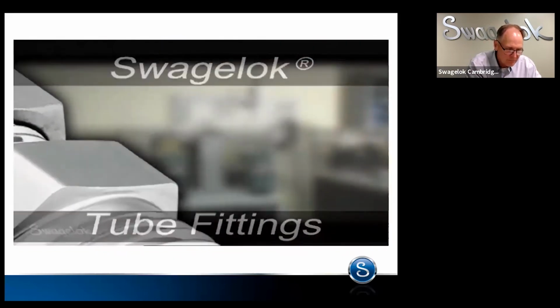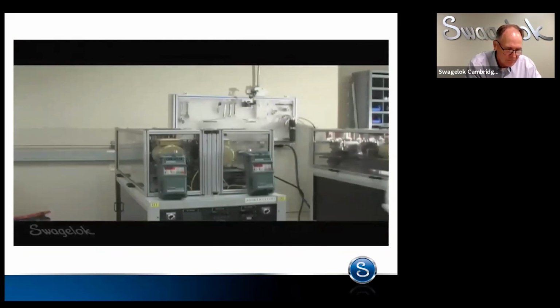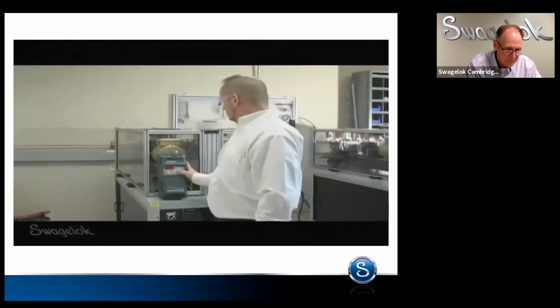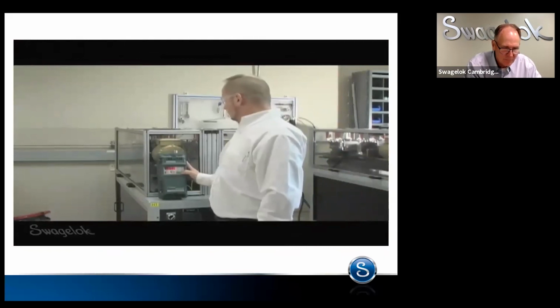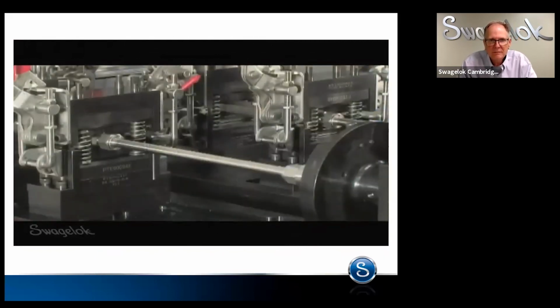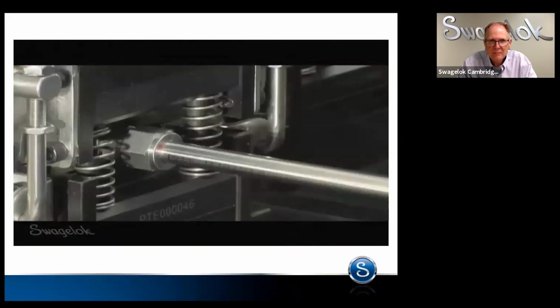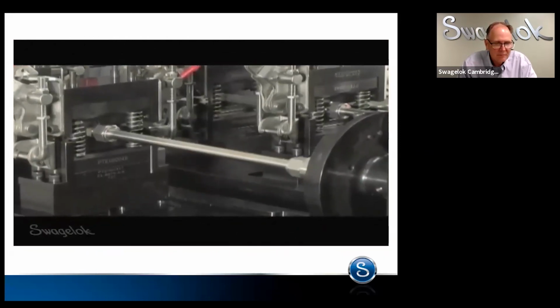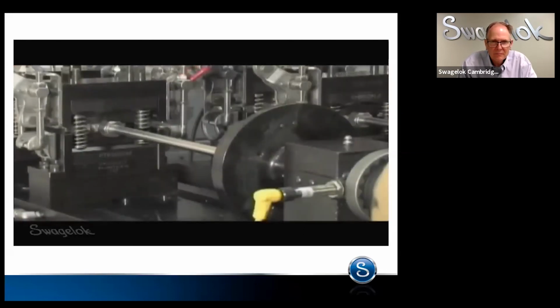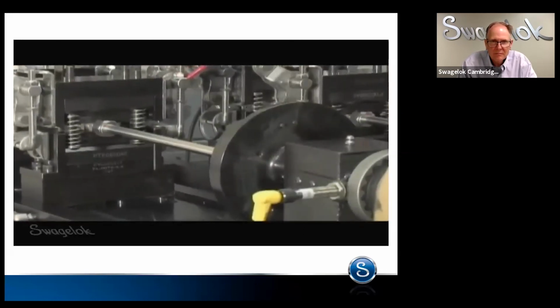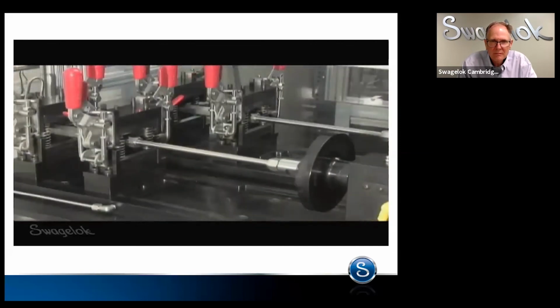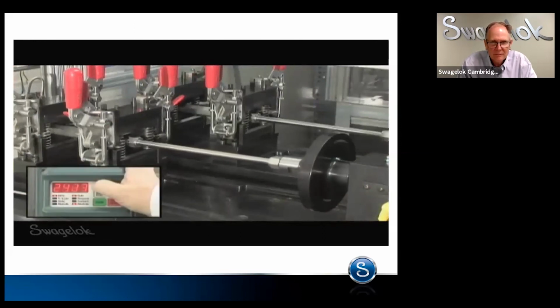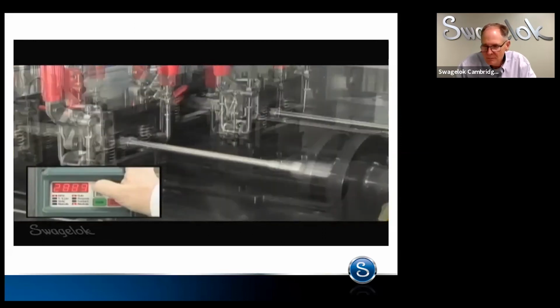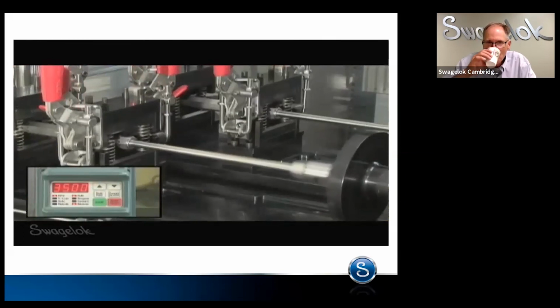Another test that was conducted at the Swagelok Company product lab included a combination rotary flex and impulse test. A half-inch Swagelok tube fitting was assembled on tubing, then attached to a stationary block. The other end of the tubing was attached to a fitting, which was then attached to a rotary wheel. The wheel has a prescribed angle of deflection and is set to create a specified stress level. The wheel rotation is quickly increased to a speed of 3,500 revolutions per minute.